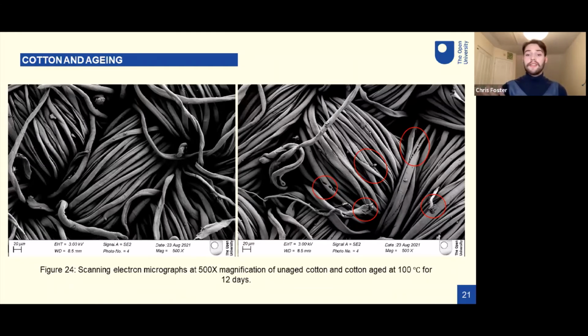To the right, you can see a 12-day aged cotton sample. This at first looks less dramatic than what we saw for the wool. However, if you look closely, you can see some breakage of the fibre in the bottom right-hand corner. This could be apparent in the unaged sample, but it does look like it's both ends of the fibre there. And even more significantly, you can see these circles in the middle of the micrograph, which show an actual separation in a single fibre itself. And this is due to the breaking of those bonds in that degradation. And this does seem concerning. So if we go to the next slide, please.